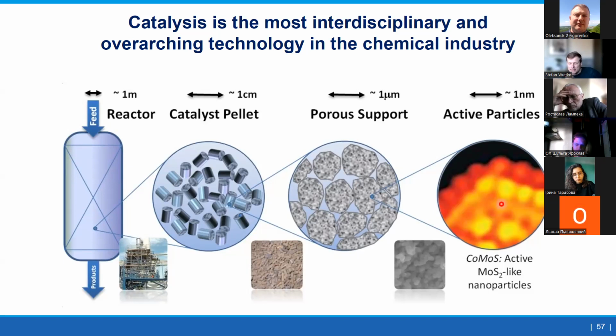Researchers were very crazy about the active sites, the species that happen, but catalysis happens at each length scale. So you have, for example, a porous catalyst where a reaction happens at the active sites, but then you have a porous support, you have the catalyst pellet and the reactor, and at the end you have a macroscopic thing. So you have reactor chemistry. Reactor chemistry is engineering. So a sample needs to enter the system. Then it needs to diffuse to the catalyst pellet, to the porous support, and then it reaches the active sites at the molecular scale. Then the reaction needs to happen, and then the product needs to be desorbed from here to here to here, and then it's going out here.